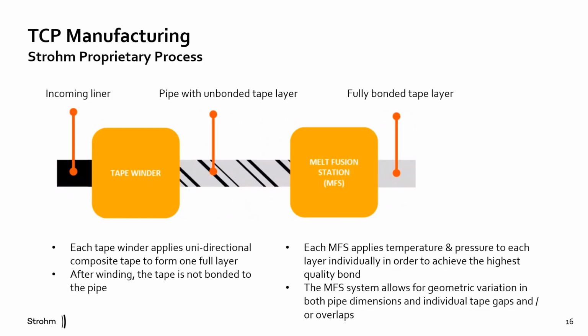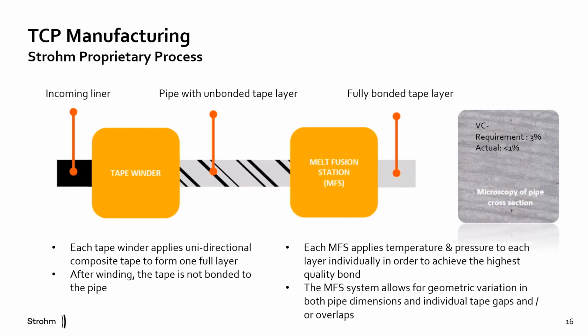But what about the quality? Consider zero porosity, defects, voids as 100% on a quality scale. In general, a composite structure is as near to perfect as it gets when it's at 97% or above. And actually, this is the number used for the structures of the aircraft that we all like to fly in. When we order our raw materials, we specify that it must be at 98%. Anything less than that can be rejected, and it's not used in our TCP. In reality though, our process of consolidation actually improves the material, and we are typically above